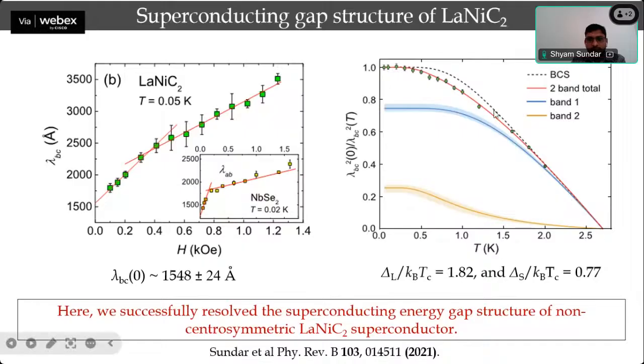And to get the magnitude of this gap, we plotted this normalized superfluid density as a function of temperature. By fitting this with the appropriate model, we get the value of the larger gap and the smaller gap, 1.82 kBTC and 0.77 kBTC. So with this research, we basically resolved the superconducting gap structure in these materials.